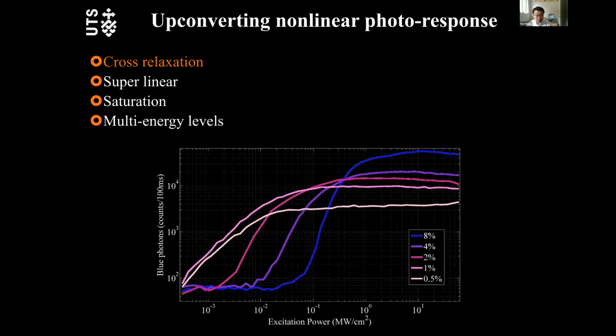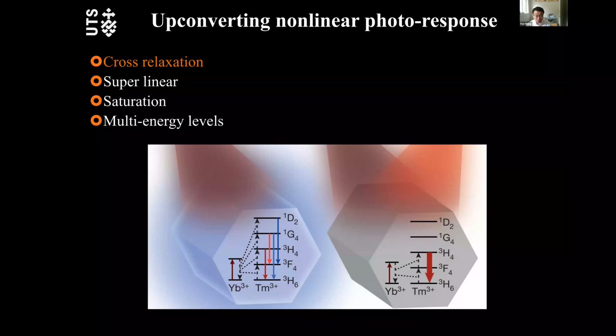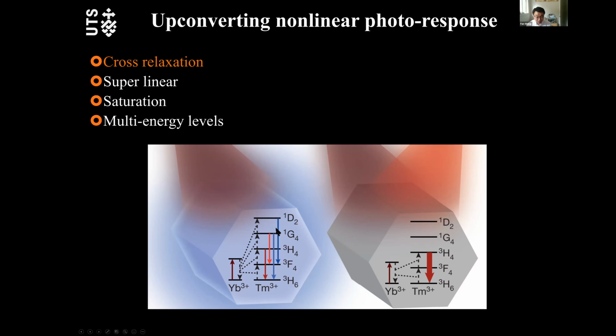So first of all, we're thinking maybe we can use cross relaxation to do that. Cross relaxation means, for example, if we have a carrier in the top level, when it jumps down to the intermediate level, the emission photon will match the band gap of another one from intermediate to bottom. So when one jumps down, it will at the same time excite another one to the medium level. Therefore, with cross relaxation, it's really easy to accumulate carriers in the intermediate level.